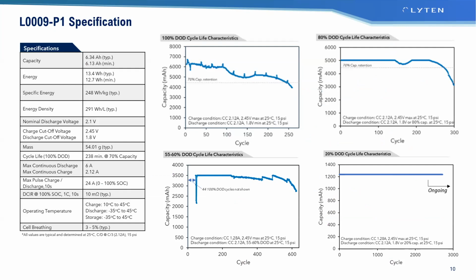And we've got cells that will make 250 to 300 cycles at a full depth of discharge, and at 20%, we're well now beyond 3,000 cycles. We think that'll go to 5,000 cycles. So this is a cell that can be used now for certain applications, things like micromobility, some stationary applications, drones, and that sort of thing. We actually have a practical cell that can be used and can be interesting.